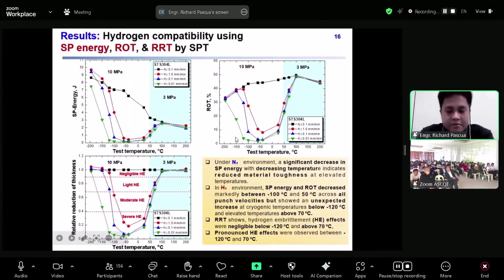If we look at the quantitative parameters in evaluating the HE susceptibility of stainless steel at different temperatures, it shows that negligible hydrogen embrittlement effects were observed below negative 120 degrees Celsius at cryogenic temperature and over 70 degrees Celsius at elevated temperatures, due to the value under hydrogen corresponding to the value under nitrogen environment. In addition, significant hydrogen embrittlement effect was observed in the remaining test conditions, especially between room temperature and negative 60 degrees Celsius, which show the severe hydrogen embrittlement in all punch velocity.